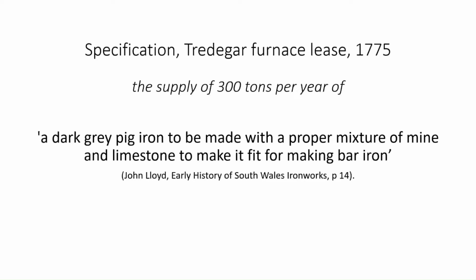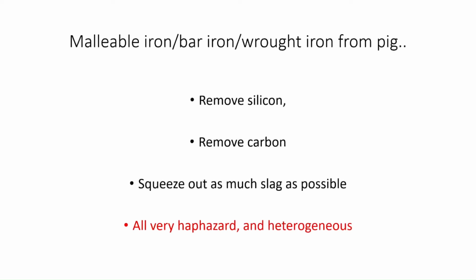Right, so we now move on to actually making bar iron. And in order to do this, you have to remove, first of all, the silicon, because you can't remove the carbon until you've removed the silicon, because you're oxidizing the carbon out. The silicon is actually much more reactive, so the silicon gets oxidized out first. Then you remove the carbon. In oxidizing the silicon and the carbon, you oxidize a lot of other impurities in the iron as well, and they will all go into the slag.